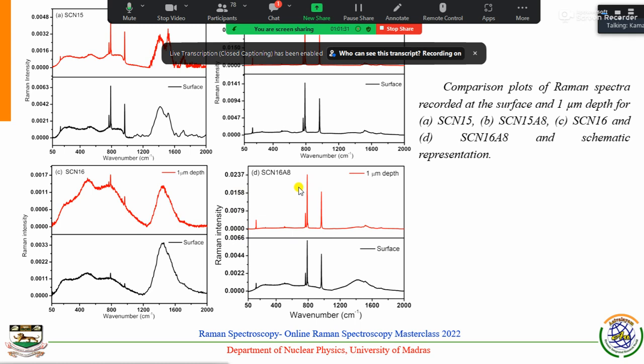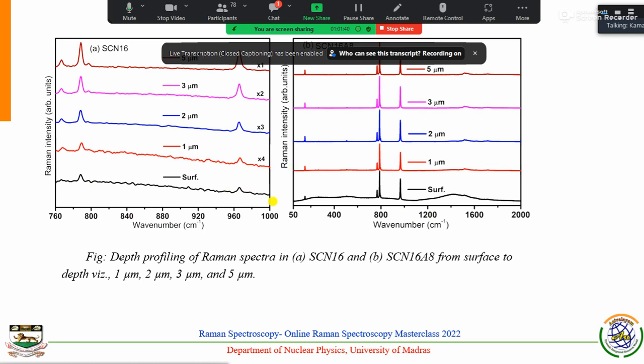After 1 micrometer we are approaching the undamaged region. Of course, the intensities must be high, as you can see here in the next slide. See, this one is the surface, the bottom one, and at 1 micrometer the intensity decreases, even though it is 4 times enhanced, it decreases compared to the surface one. After that, if I approach 2 micrometer, 3 micrometer, now the intensity increases because we are approaching the undamaged region.